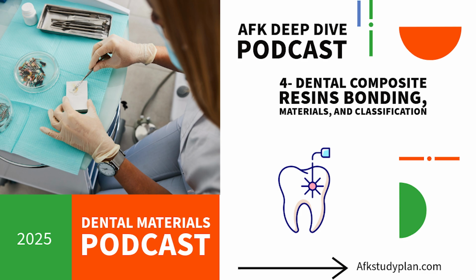And the latest evolution? Nanocomposites? Yes, or nanohybrids. These use nanoparticles just 1 to 100 nanometers in size, really tiny. Because they're so small and often specially treated, you can pack a lot of them in, over 60% by volume, sometimes near 80% by weight. Wow, and the benefit? You get the amazing polishability and optical properties, like translucency, similar to microfills, but with mechanical strength that's good enough for posterior stress-bearing restorations. Often, they're nanohybrids, mixing nanoparticles with slightly larger particles. Very advanced stuff. Incredible how particle size makes such a difference.